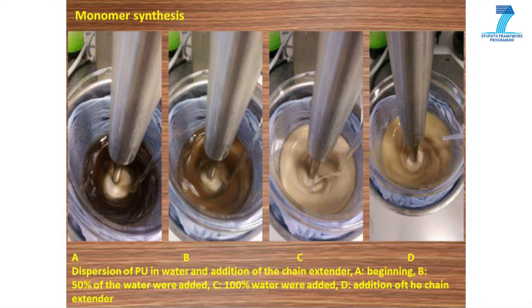The next step in resin synthesis route consists of an addition of water in order to obtain dispersion of nano-sized polymer particles in water. Chain extending step is optional and serves to significantly increase molecular weight. Last but not least is the removal of organic solvent by distillation in order to significantly decrease health risk for the end users. The obtained viscous liquids are then used as a binder in coating formulations.